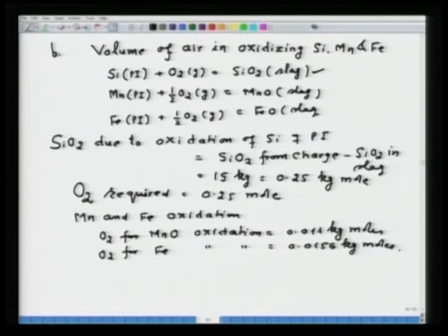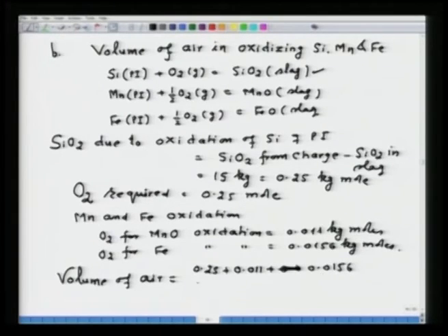So, now there is no problem. Volume of air as required in the problem will be equal to 0.25 plus 0.011 plus 0.0156, divided by 0.21, multiplied by 22.4.